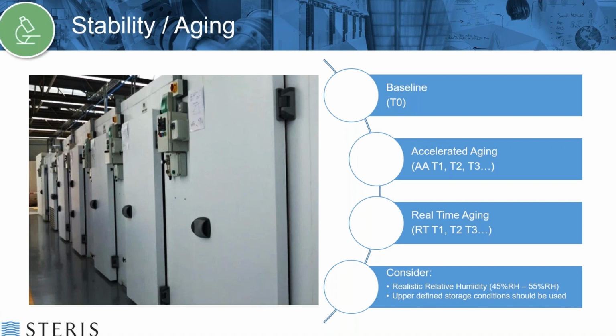So a couple things to consider. The ASTM standard for accelerated aging, which is F1980, now recommends using realistic relative humidity for your accelerated aging. Previously, it recommended using lower relative humidity, but since 2021, it recommends using 45 to 55% RH for your relative humidity. It does give you the caveat that you can define something else if you have data to support using a different relative humidity, but it does recommend using 45 to 55% RH at this point.